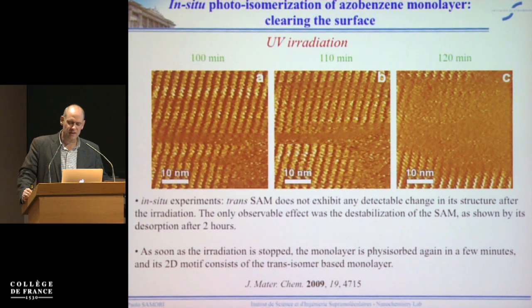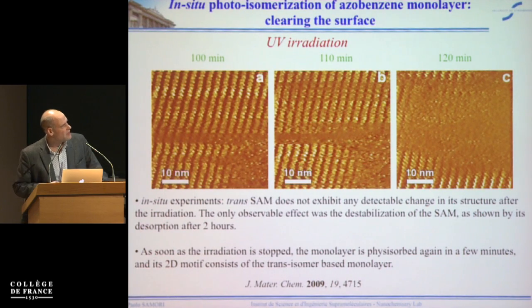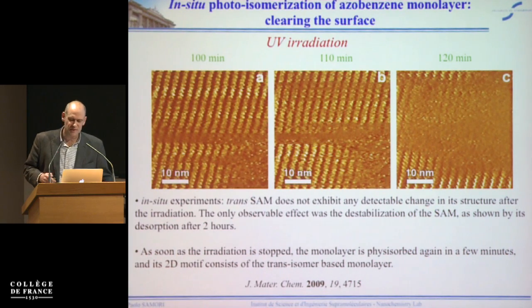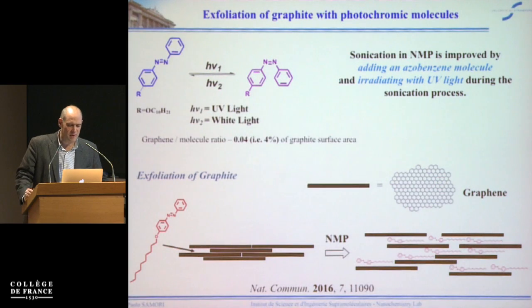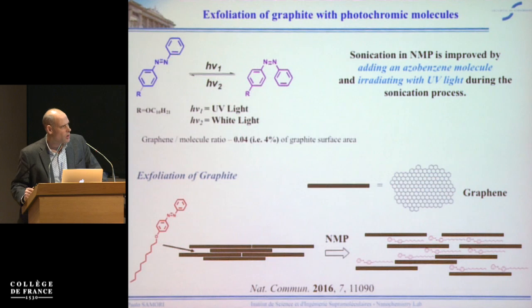When we turn off the UV light, the cis state is metastable, and so gradually the monolayer of the trans molecule was reformed spontaneously. Anyway, the piece of information we learned out of this study is that we can play with the alkyl substituted azobenzene, because in the two states there's a different energy of adsorption on the basal plane of graphite or graphene. And so my idea was very simple: long aliphatic chains to promote the intercalation of the azobenzene between layers of graphene during the exfoliation, and then at that point we can play with isomerization.